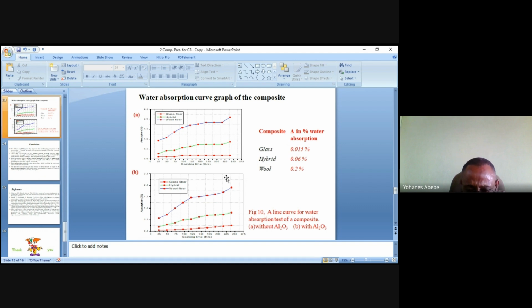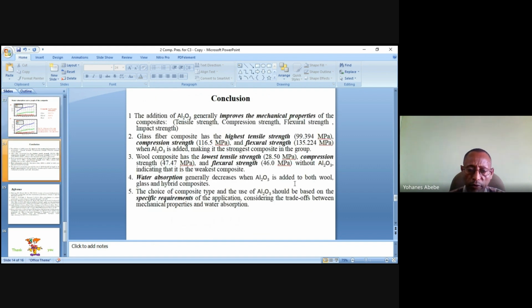But when we see the addition of nano alumina, the curve shows improvement. The curve shows that the glass fiber is 0, the wool fiber is 0.2, and that of the hybrid is 0.06. This graph shows the water absorption property without the addition of nano alumina, whereas this graph shows the water absorption property with the addition of alumina. This is percent improvement in the composite obtained from the glass fiber composite, the wool fiber composite, and that of the hybrid composite. So in general, the addition of alumina improves the mechanical properties of the composites: the tensile strength, the compression strength, the flexural strength, and impact strength all show improvement.